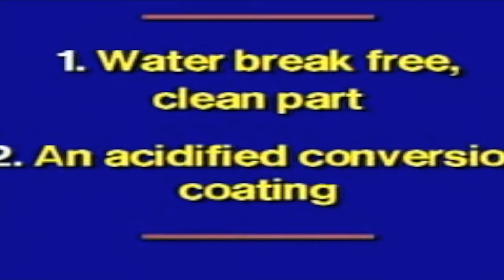With solvent-based paints, a minute amount of oily residue was easily dispersed by the solvent in the paint, and good paint adhesion was often achieved. However, underfilm corrosion protection was poor. The need for better corrosion protection led to the development of alkaline cleaning to remove organic soils and acidic conversion coating of metal substrates to achieve 1, a water break-free clean part, and 2, an acidified conversion coating to convert the metal surface to a less conductive state, which helps to inhibit the spread of underfilm corrosion. The result is a combination of good paint adhesion and improved underfilm corrosion resistance.